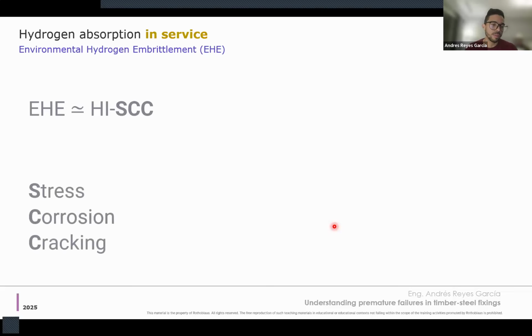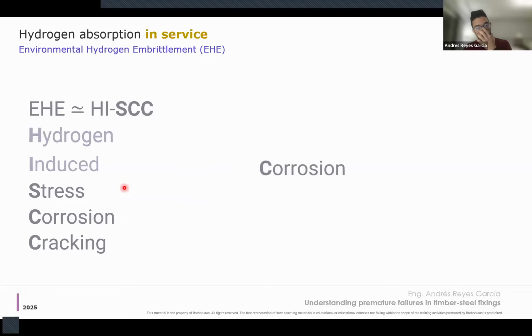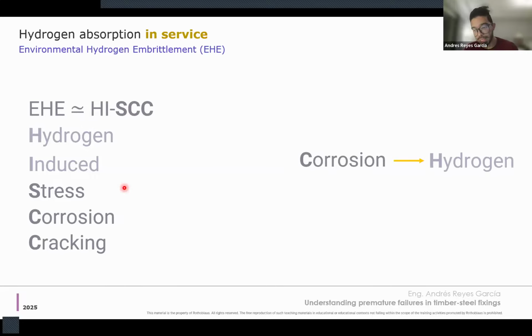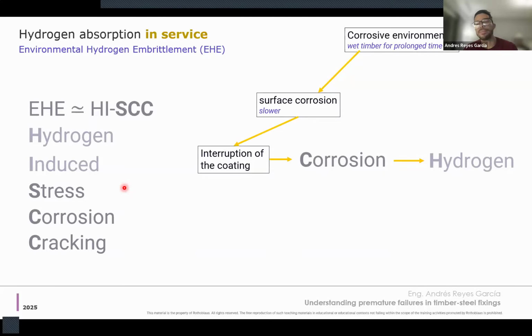Another way to explain it comes from its second name, which is hydrogen-induced stress corrosion cracking. So we need stress, we need corrosion. These two factors will induce cracking, and they come from hydrogen. What happens is that the corrosion, mostly of the zinc, produces hydrogen, and in the presence of an interruption of the coating, that might come from a corrosive environment of wet timber for a long time, which will produce some surface corrosion but it will take some time, it will then lead to failure.